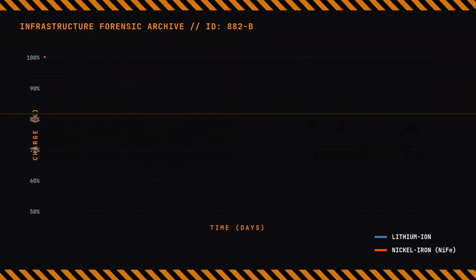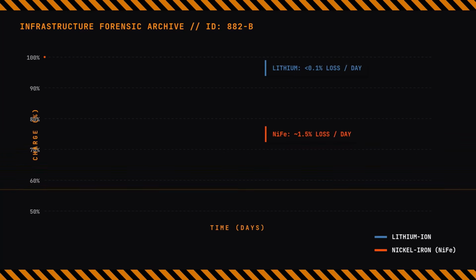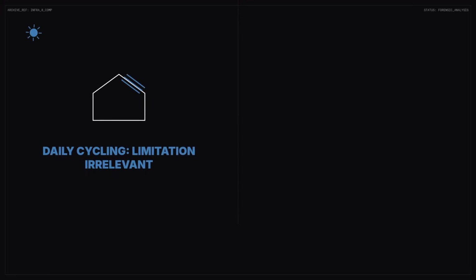But what about self-discharge? The rate at which the battery loses its stored energy when sitting idle. This is the nickel-iron cell's one genuine limitation. It self-discharges at approximately 1 to 2% of its stored charge per day at room temperature, compared to less than 0.1% per day for a premium lithium iron phosphate cell.